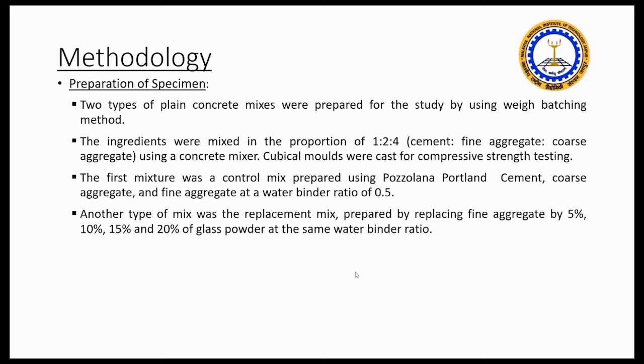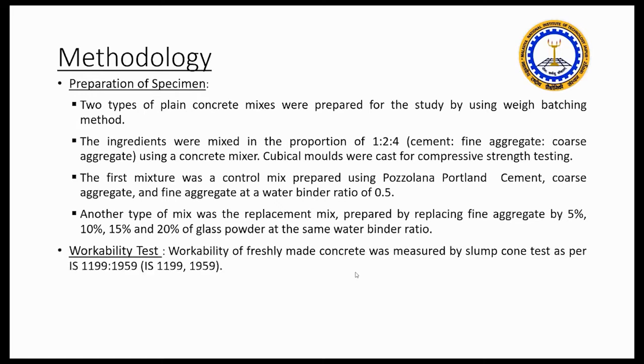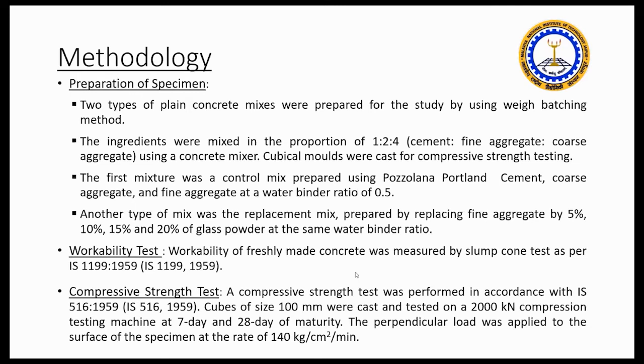Another type of mix consisted of glass waste, replacing fine aggregate by 5, 10, 15, and 20%, at the same water binder ratio of 0.5. This is the methodology for the workability test, which we conducted on the freshly made concrete, measured by the slump cone test as per IS 1199. Compressive strength test was conducted in accordance with IS 516:1959.